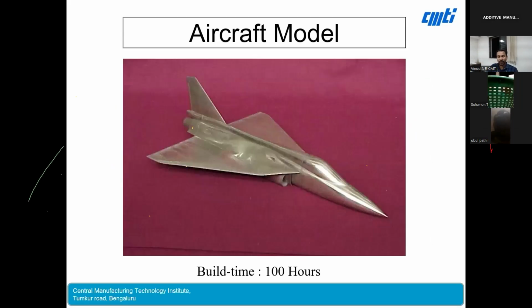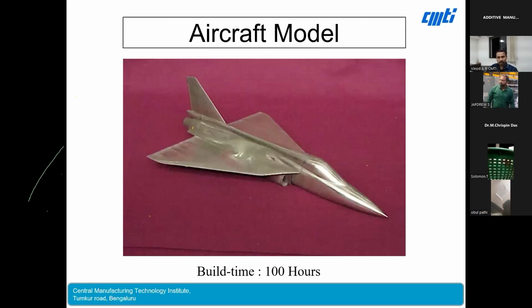Now I will give you case studies, typical industrial applications we have worked on at CMTI. You can see this is a 1:30 scale down model of an LCA aircraft. It is around 500 mm long. In our machine, we have a limitation of 250 by 250, so we split the part into three, 3D printed them, and then assembled them to make this 500 mm long part. This 1:30 scale down model was used for wind tunnel testing.